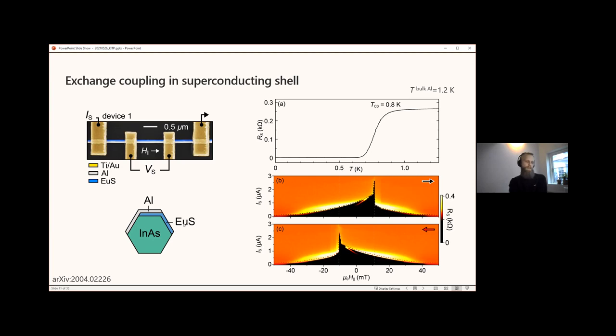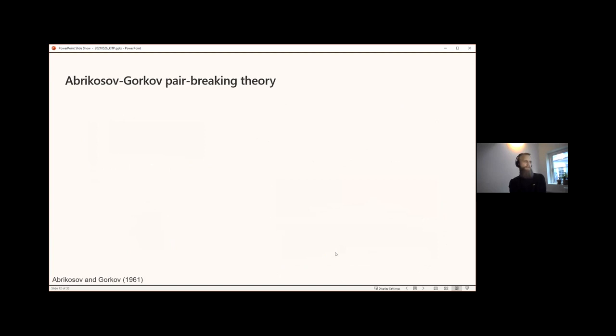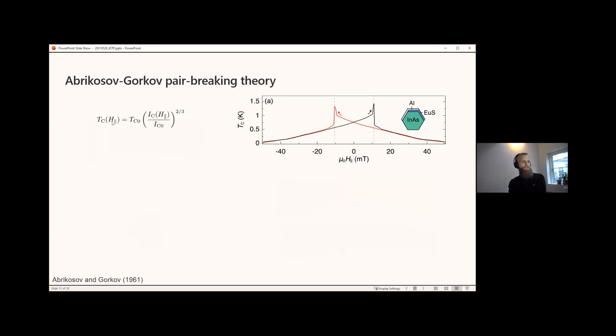The question still remains, though: how big is the effective field? After we took these measurements, we realized that we can extract the effective field from the critical current measurements by the following procedure. We can take the following dependence of the critical temperature as a function of magnetic field and deduce it from the critical current that I just showed you before. And by doing so, we get the following critical temperature curves.